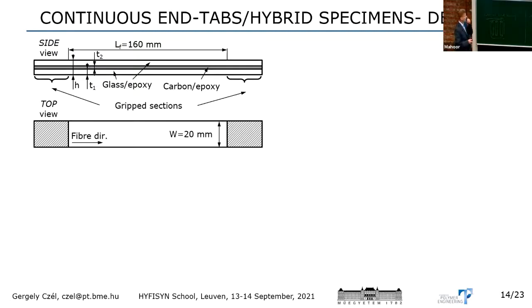So our concept for the test specimens for measuring the failure strain of UD composites is a delaminating hybrid composite, not a fragmenting one, but a delaminating one. So we need to design the specimens so that we will get delamination at a given load or given strain, which hopefully corresponds to the real failure strain of the carbon epoxy layer.